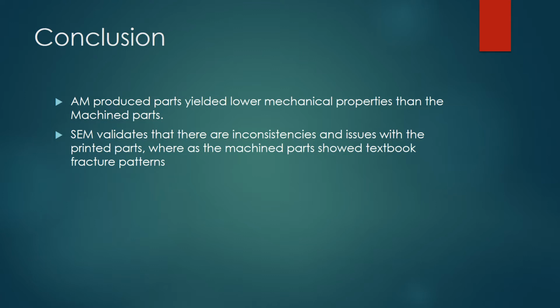To summarize our results and tie everything back to our hypotheses, we did see that the additive manufactured produced parts yielded lower mechanical properties in comparison to the traditionally machined parts. And we also found that the SEM validated that there are inconsistencies and issues with the printed parts, such as lots of voids, whereas the machine parts were really textbook fracture patterns.